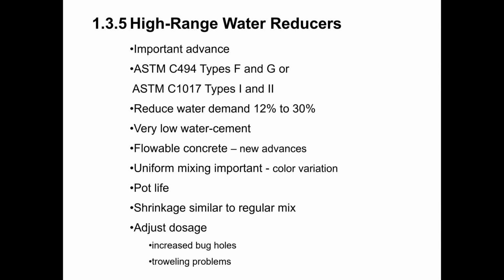Over the years, admixture manufacturers have refined high-range water reducer chemistry such that they still have a pot life, but it's much broader. It lasts for a longer period of time, and once it starts wearing off, it doesn't wear off quickly. It's a more gradual wearing off, so that if you recognize that you're starting to lose slump because the high range water reducer is wearing off, then you've got more time to get the concrete out of the truck and get it placed and finished than maybe you would have 30 years ago, 40 years ago, when high range water reducers first started being used.